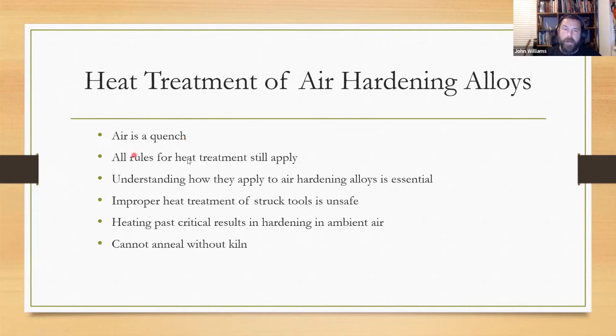All the rules still apply. You can still form pearlite with air hardening steels. You can still anneal it, for instance. But to anneal it, you've got to have the annealing process go over a 24-hour period in an electric kiln, where it's coming down 15 degrees or such and such degrees over every 15 minutes. So you can't do that in a shop setting. And that's really important because if you're not understanding what's going on, you could make an unsafe tool.